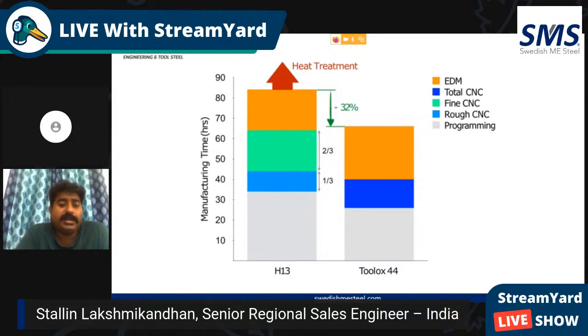So here you are comparing Toolox 44, which is delivered at 45 HRC, to an annealed condition H13. So what do we get here? As you can see, the manufacturing time is given on the y-axis. You can see the programming time: you need not do two programmings as compared to H13, because in the annealed condition you need to do programming, and again after heat treatment you need to do another set of programming. That is not required here. You can go with one set of programming. You can go for the direct final CNC. You need not go for rough and final. You can directly go for a final CNC.